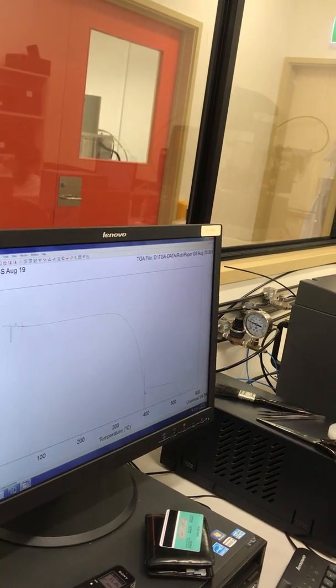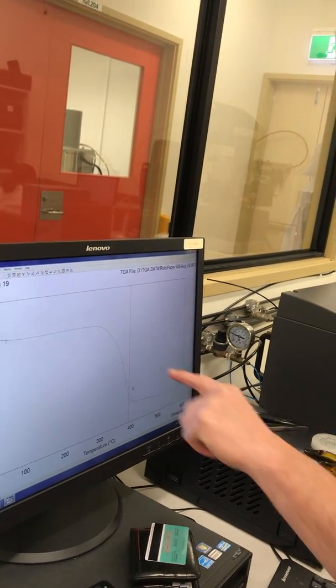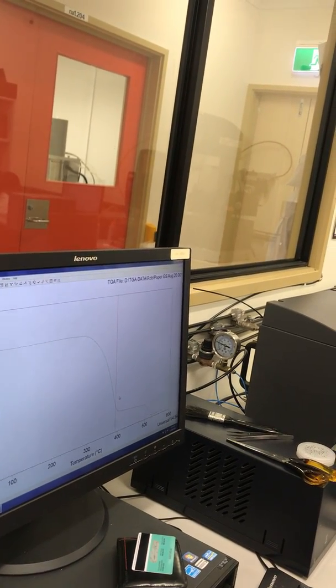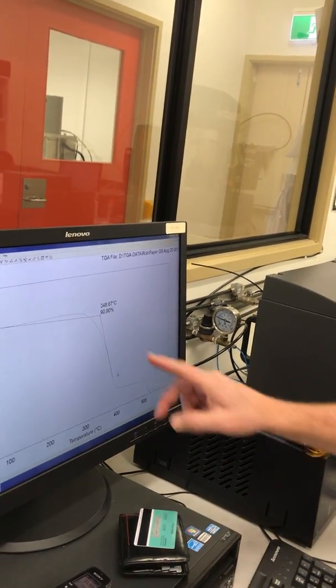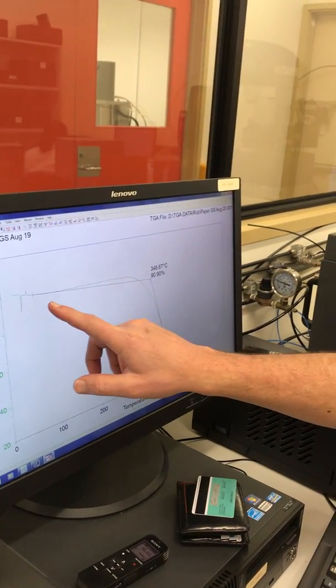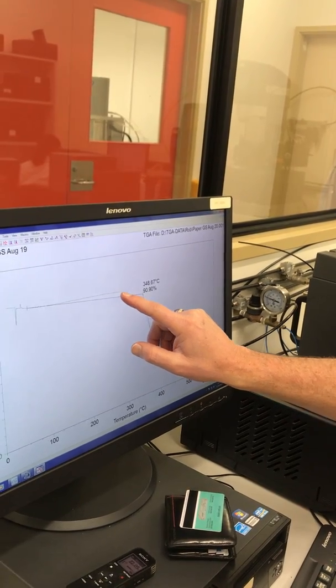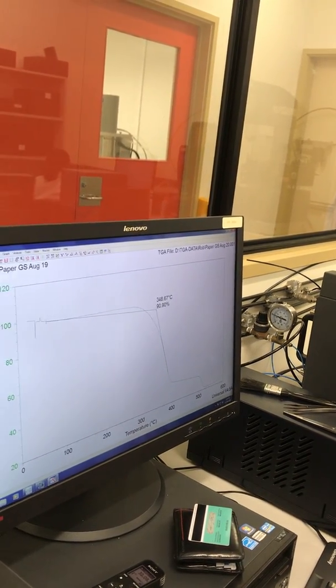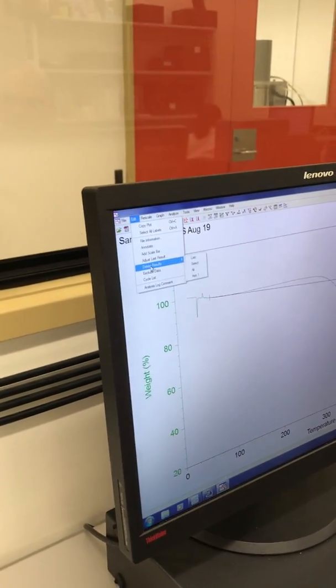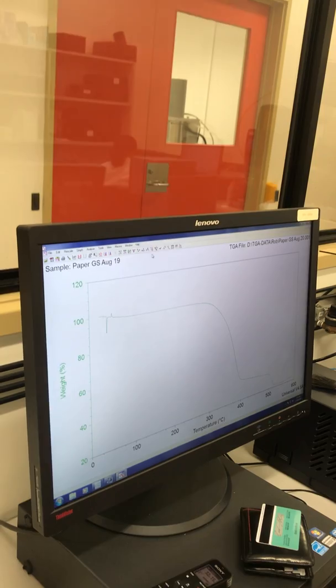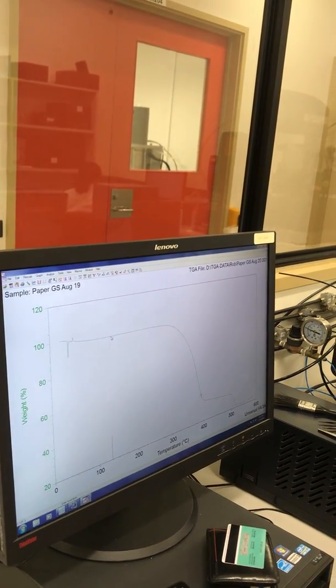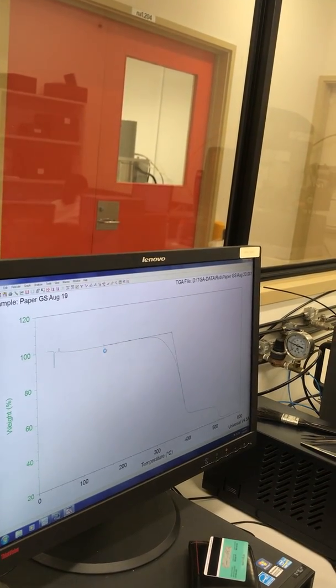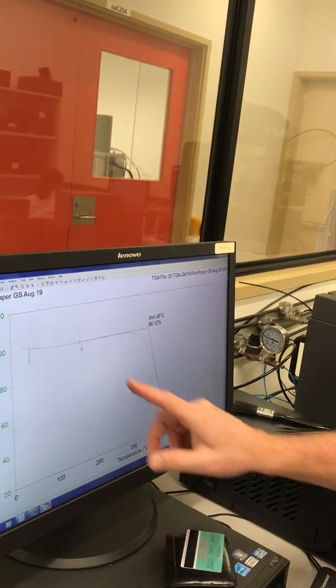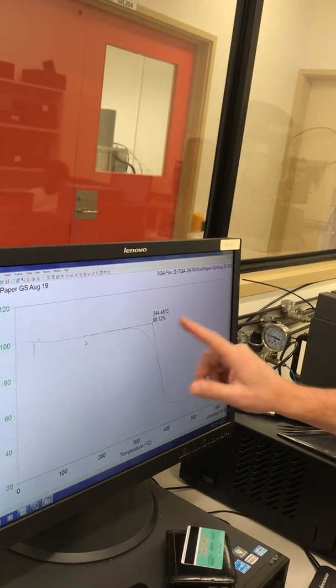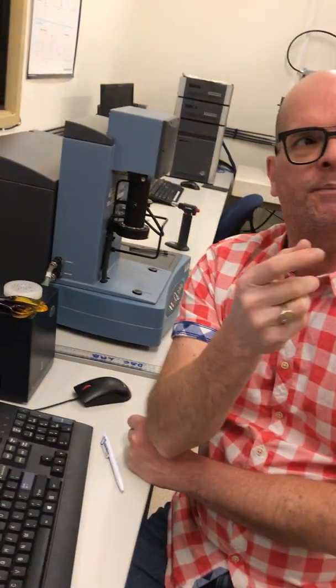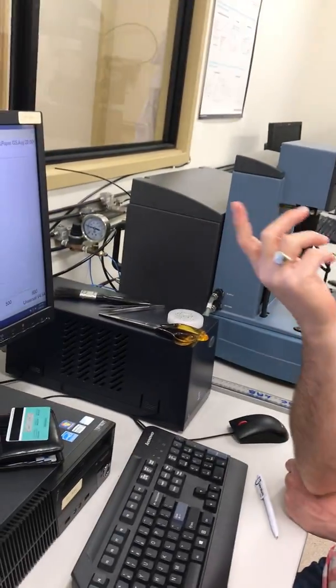I'm going to draw a baseline along here, along there, and see when the onset of the decomposition started. It says about 350, but I'm not happy with the way this one drew the baseline. It hasn't really followed that along there. I can't really adjust that, so I'm going to edit, delete the last result, and do that again, and bring this one a bit further here. So it follows that a bit better, about 4 degrees difference. It's drawn a nice baseline here and there. So the decomposition of paper in nitrogen is 344 degrees.